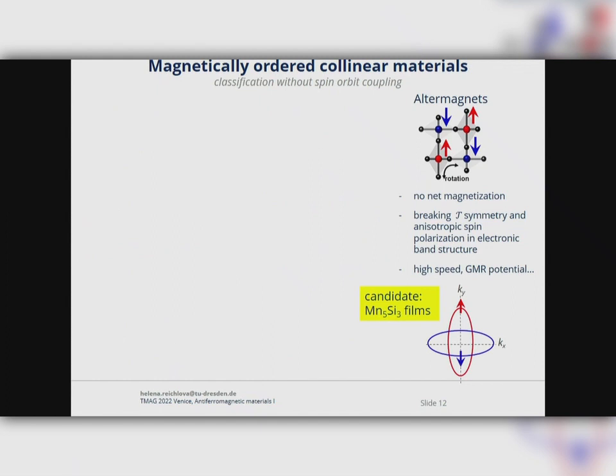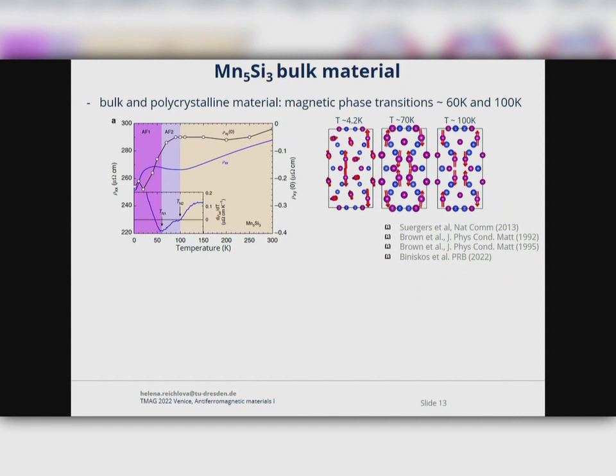And so now the experiment, what I will speak about is one of the altermagnetic candidates, which is Mn5Si3 thin films. So before I go to the thin films, let me briefly introduce the Mn5Si3 bulk material. It's a relatively well-known material which was studied, for example, by these gentlemen. And it shows two magnetic transitions, the first at approximately 60 Kelvin. And this magnetic transition is from the paramagnetic phase to the collinear and then the non-collinear phase.